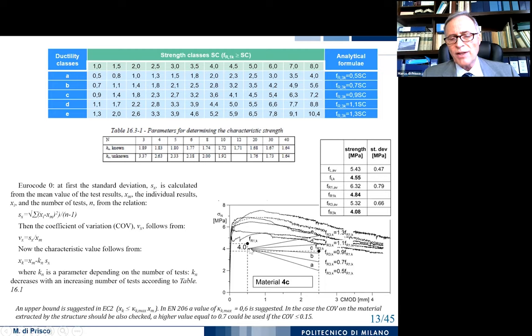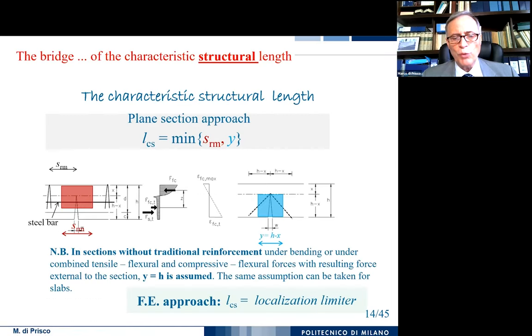And in this case, we have a class 4c because we have, as you can see, a ratio between FR3k and FR1k, which justifies the position of the letter c. So 4c means that I have an FR1k equal to 4 megapascal, and I have an FR3k which is at least 0.9 FR1k, so around 3.6 megapascal. So this is the classification we adopt.